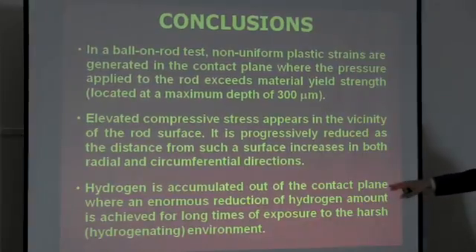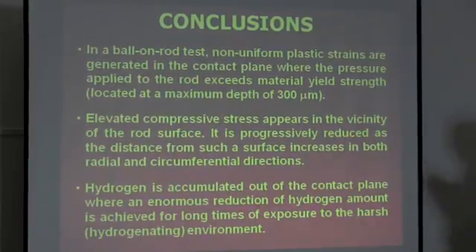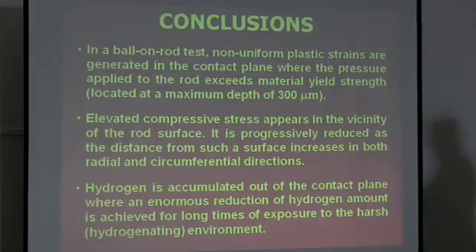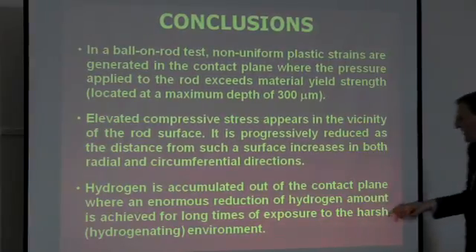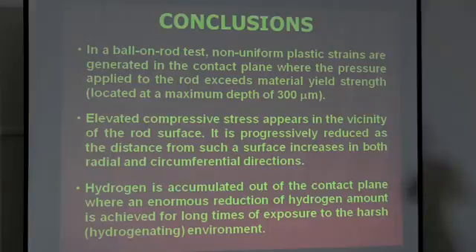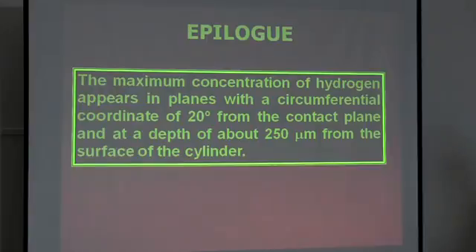Hydrogen is accumulated out of the contact plane, where an enormous reduction of hydrogen amount is achieved for a long time of exposure to the harsh hydrogenated environment. Due to the strong compressions, we see that these boundary conditions, heavy compressions, predominate over the inward gradients. The key point here is the amount of hydrogen available for inward diffusion, more than the velocity of inward diffusion. That's the real conclusion. And now the meta-conclusion, the epilogue, the conclusion over the conclusions.